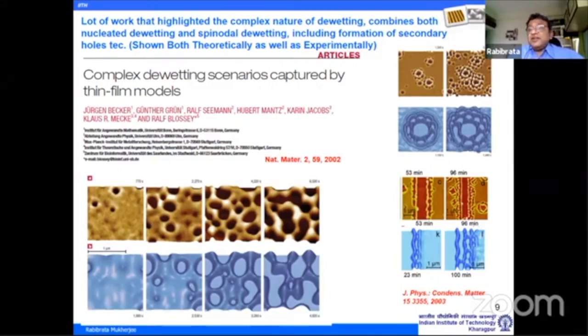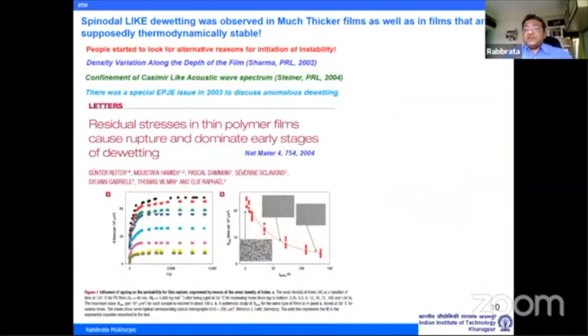The reasons for dewetting to a large extent are still unknown, because it shows, as we discussed, that the dewetting should take place only when the interaction is attractive. That means that you have a film on a non-wettable surface, but there are a large number of examples where you see dewetting even on a wettable surface. So people have started to argue probably it's the residual stresses, non-equilibrium configuration of the polymer chains during the spin coating process, and everything might be reason for dewetting. And trust me, it is not yet resolved fully.